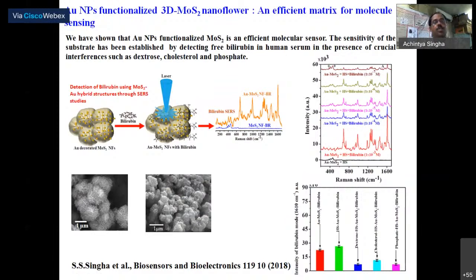Next. Yeah, in this work we use the MoS2 nanoflower, and we decorated the MoS2 nanoflower with gold nanoparticles, and that gold nanoparticle acts as the substrate and enhances the Raman signal. We use bilirubin as a probe molecule, and we can see up to very low concentration we can measure the bilirubin molecule even in the presence of human serum, dextrose, cholesterol, phosphate. We know that those components are present in our blood.